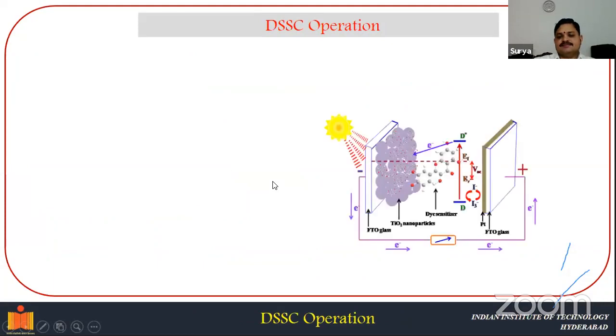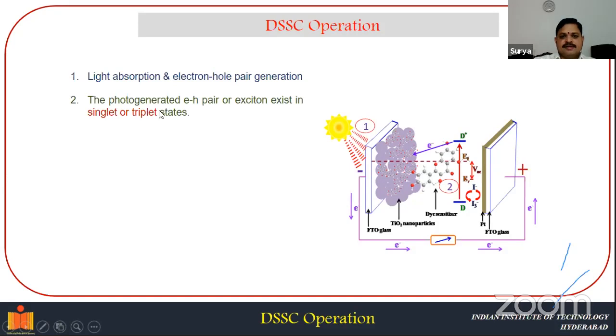So how does a DSSC operate? The question is how a dye sensitized solar cell operation takes place. Initially, light absorption and electron hole pair generation happen. As soon as the light falls on the solar cell, which consists of dye, active material, and electrolyte, the electron hole pairs will be generated. For instance, if I consider the N719 dye, it will have the ground state and the excited state. In the excited state you will have the singlet state and the triplet state. The photo generated electron hole pair, we can also call the pair of electron hole an exciton. This exciton exists in the singlet or triplet states.